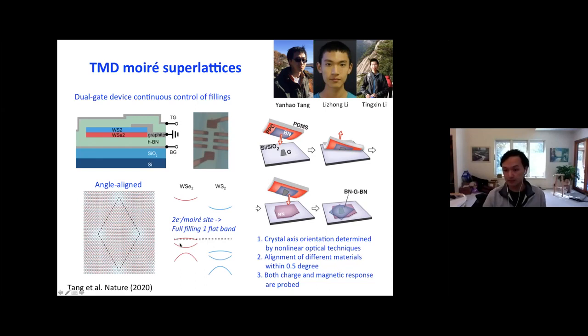And just a couple more words about the fabrication and the measurement. So this is actually not twisted bilayer graphene. For those experimentalists who are interested: if you make twisted bilayer graphene, you usually start with a single piece of graphene. You tear them apart, then you rotate the angle and restack them together, right? But for this material, you can see that it actually consists of two different materials. So we have to predetermine their crystal orientation before we assemble them together, right? Because we have to target them to be near 0 degree.